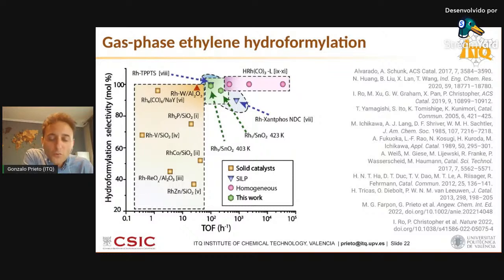Now, the rhodium on tin oxide single atom catalyst we developed, those are the green dots and the green shaded area, they outperform by a lot these previous solid catalysts, by bringing selectivity to essentially 100%, and not at the expense of turnover frequency, but rather improving turnover frequency by orders of magnitude too. Actually, this is a performance which places them on par with those of the molecular hydroformylation catalysts operating in liquid media, either in solvent media, so the classical homogeneous catalysis, that's the data points within the pink block. Those are the most active and essentially fully selective.